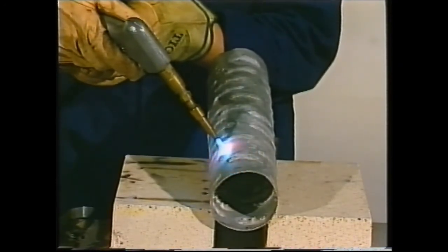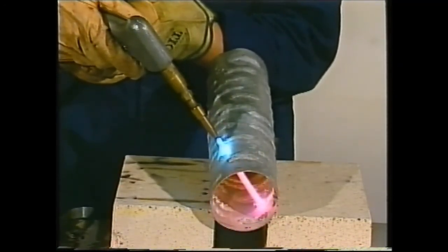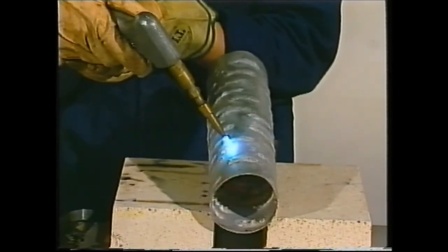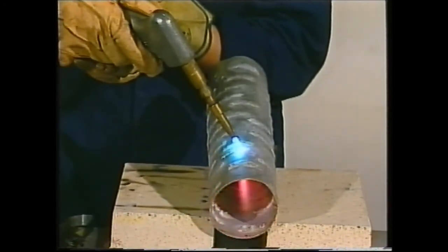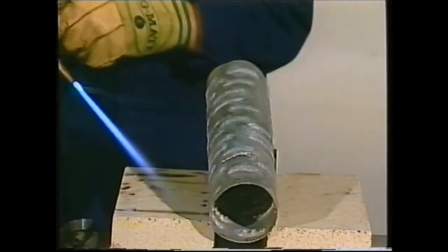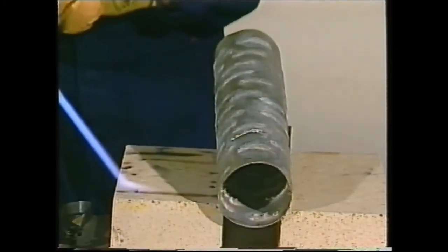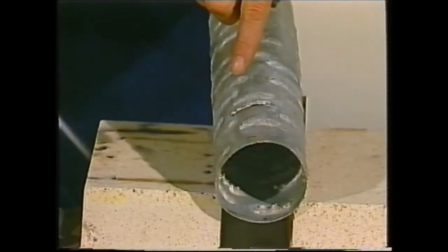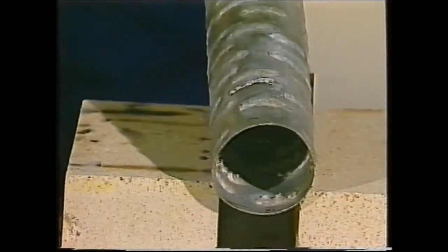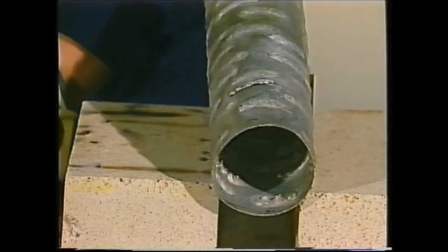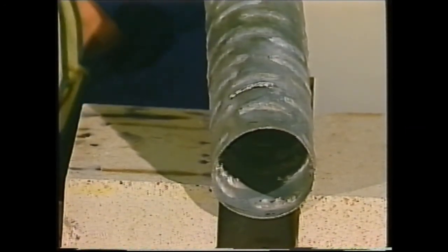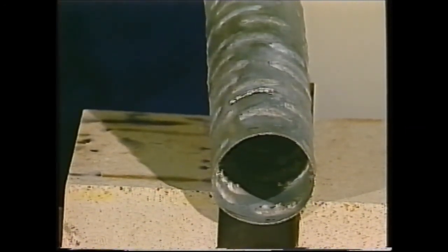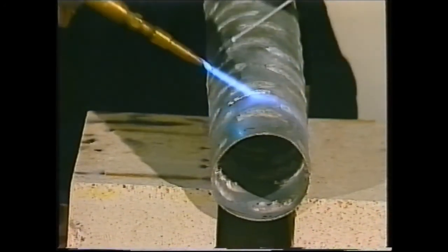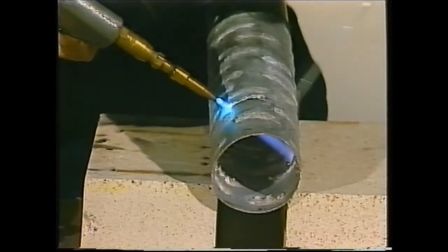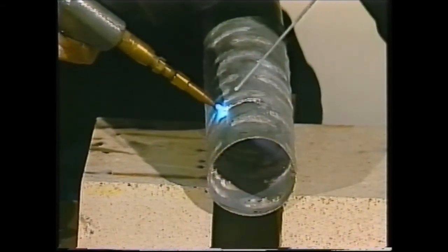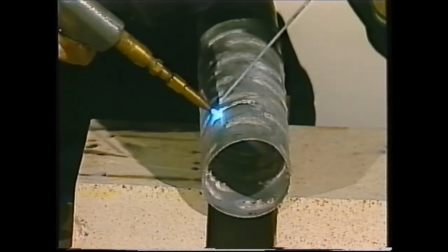Now, if you were to do this with a conventional oxy torch, you would just collapse a large part of that. This torch just blows a small hole the size of the flame. And as you can see, you can use the torch to actually controlled melt a slot in the material. Now, we're just using standard aluminium filler rod, 5356 rod, that you can get from any welding outlet. Very important to say that we don't require any specialist rods for this. In fact, an old aluminium coat hanger works perfectly well.